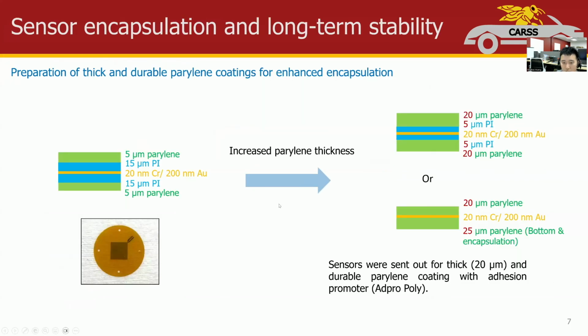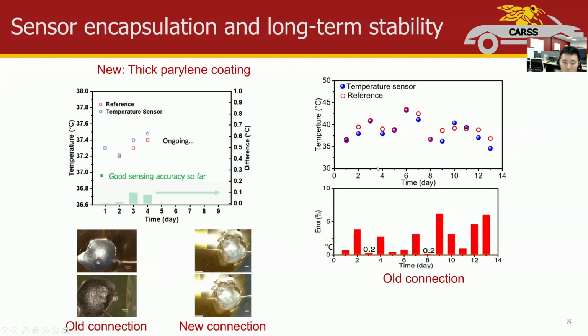Based on this, we then change our Parylene layer from 5 micron to 20 micron, as you can see on our right-hand side. Here we have 20 micron Parylene on both sides of our sensors. Subsequently, we re-evaluated the long-term stability of the sensor. The data indicates that using a thicker layer of Parylene significantly enhances performance. Clearly, our newly designed temperature sensor equipped with this thicker Parylene coating demonstrates improved longevity. Long-term testing is still ongoing, and we will provide a comprehensive summary upon completion.